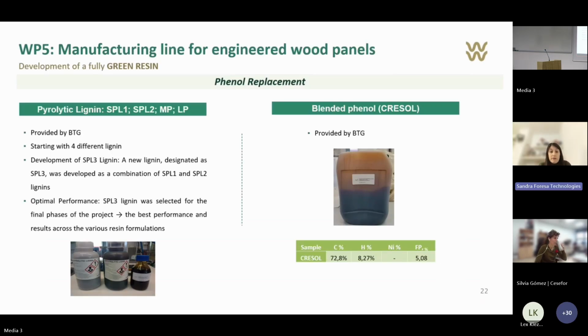For phenol replacement, the project started with 4 different pyrolytic lignins. However, in the middle of the project, a combination of 2 of them, called SPL3 lignin, resulted in the best lignin to continue with, because we obtained the best results. We also tried blended phenols or cresol, and both of these samples were provided by BTG company, like mentioned before.